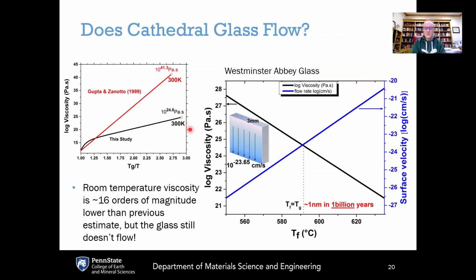And this is rather surprising compared to what had been published previously by Gupta and Zanotto, using their modern soda-lime glass and the models and the experimental data that were available at the time. What they had predicted was a room temperature viscosity of 10 to the 41.3 Pascal seconds. And that extremely high viscosity was what gave the result that it would take 10 to the 23 years for the glass to flow. Keep in mind that was about 9 to 10 orders of magnitude lower or faster compared to the original estimate by Zanotto, which was assuming just the liquid state of the viscosity. So this was already about 9 to 10 orders of magnitude faster.